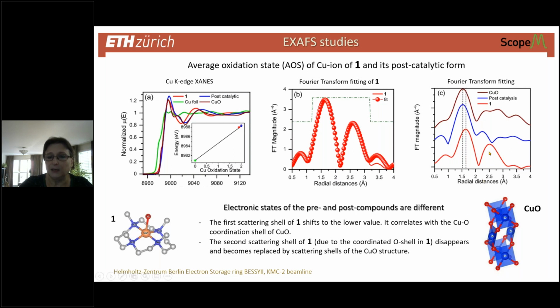Then, the second scattering shell of compound 1, which is due to this bond, this coordination shell, basically disappears. And instead, we have a few scattering shells that also fit quite well with the values of the copper oxide structure. This is the main message that you can read from this slide.